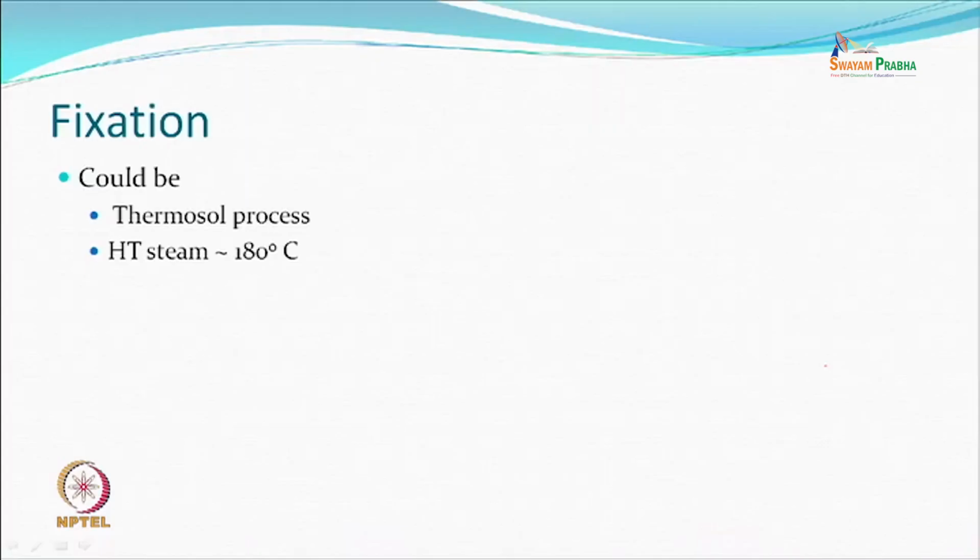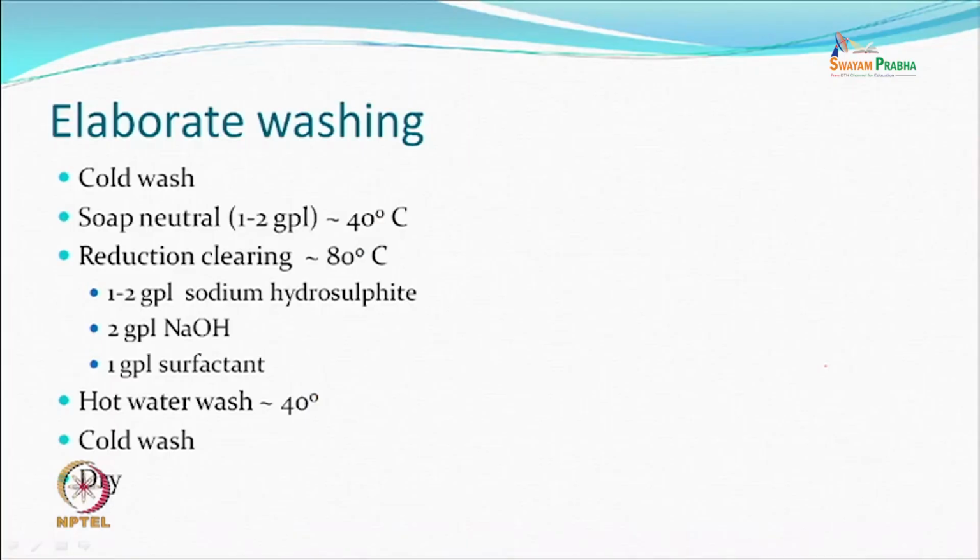For fixation, you can use the thermosol after printing directly, which is possible, or high temperature steam. The way polyester is fixed after printing and dyeing, the same process can be used there. So that's the fixation. The washing is elaborate in the sense that everything is being done, including cold wash and then a neutral soap.